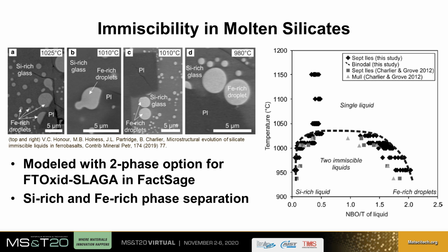Researchers in earth and planetary science have reported a miscibility gap in the molten silicate system where silicon-rich and iron-rich phases separate. To account for this liquid-liquid immiscibility, the thermophysical modeling in this study was done with a two-phase slag instead of treating the molten phase as being uniform in composition.